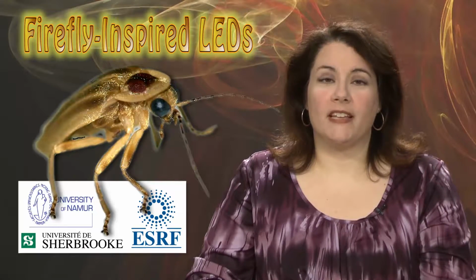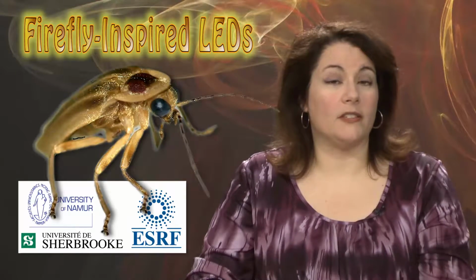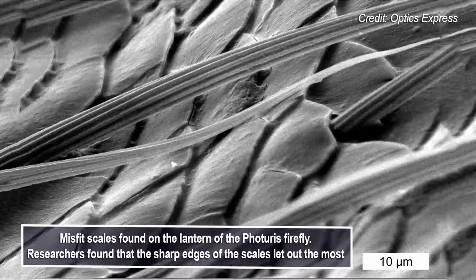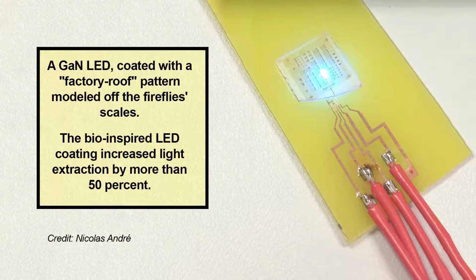Researchers from Belgium, France, and Canada studied the internal structure of firefly lanterns, the organs on the insects' abdomens that flash to attract mates. They identified an unexpected pattern of jagged scales that enhanced the lantern's glow and applied that knowledge to LED design to create an overlayer that mimicked the natural structure. The overlayer, which increased LED light extraction by up to 55%, could easily be tailored to existing diode designs.